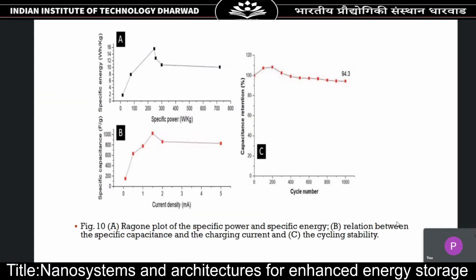And this shows the Ragone plot. A Ragone plot is nothing but a plot of energy density versus power density. So this was plotted for the device, and it also shows the cycling stability. You can see that the profile is almost flat, right? Up to 94% capacitance is retained.